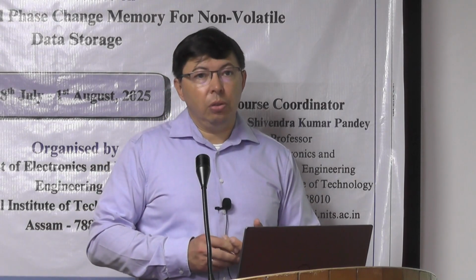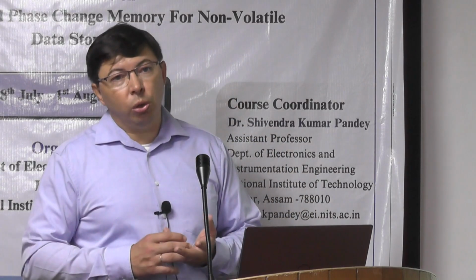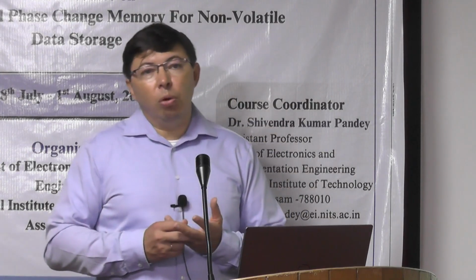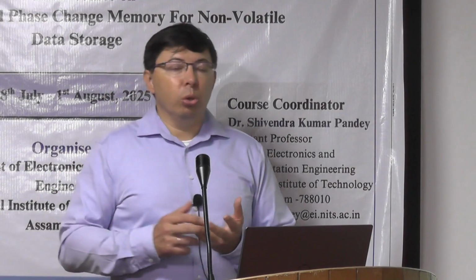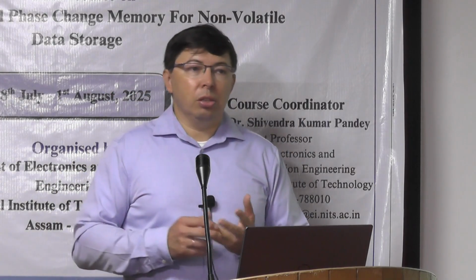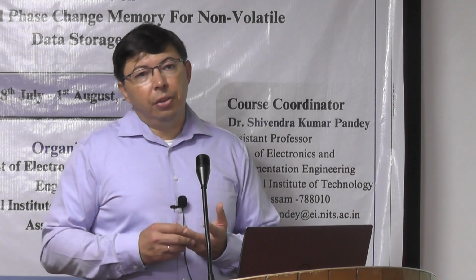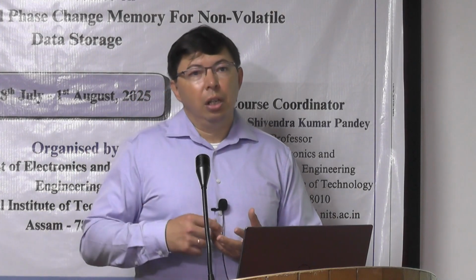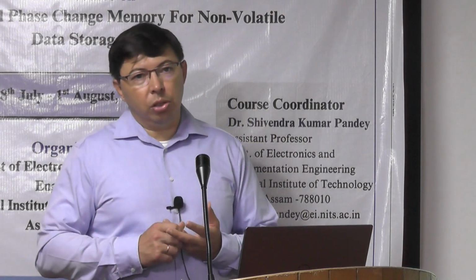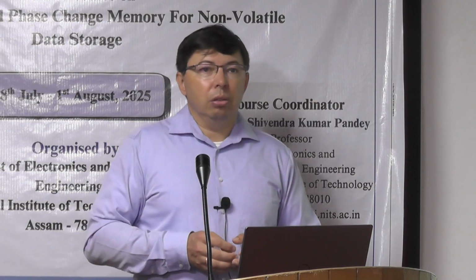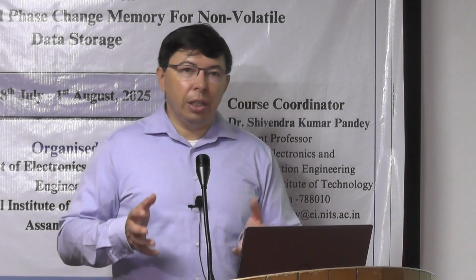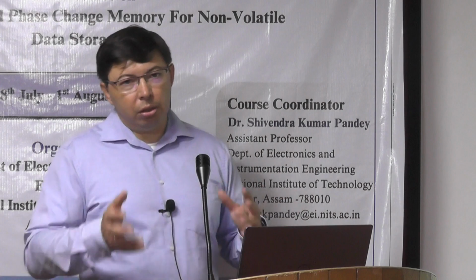Okay, so it shows dual behavior. Only the germanium telluride does not show it, because it contains very few vacancies. Sometimes some reports say 10%, some say no vacancies. So this is the effect of vacancies on the metal-insulator transition, or non-metallic to metallic. It's nice to say insulator, but non-metallic can be insulator.